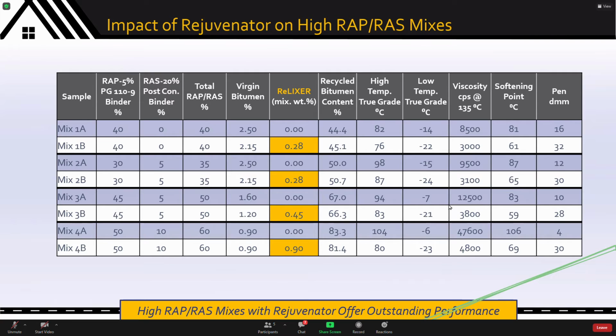What you can see is the dramatic lowering of viscosity from about uncompactable 48,000 viscosity. You're moving it more in line with, let's say, a traditional PMB type viscosity that you can pave with. You can see the attendant change in low temperature properties, and most importantly, you can also see the penetration values from almost a 0 pen material. It's making the effective bitumen almost a 30 pen type material.